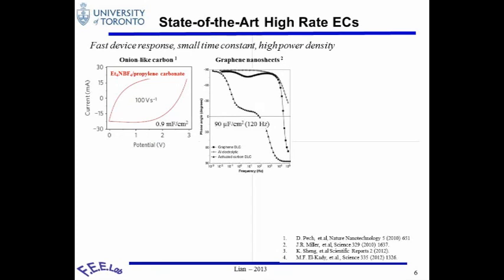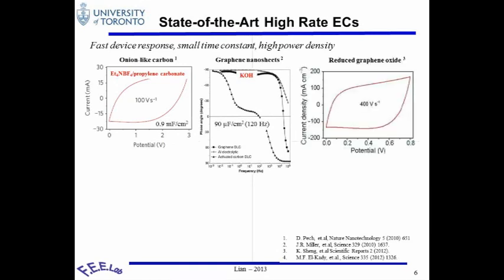So this is at 120 hertz with 90 microfarads, using KOH as electrolyte. These kinds of efforts demonstrated that yes, supercapacitors can go very, very high rate. So that sort of inspired many more papers and applications in this route.